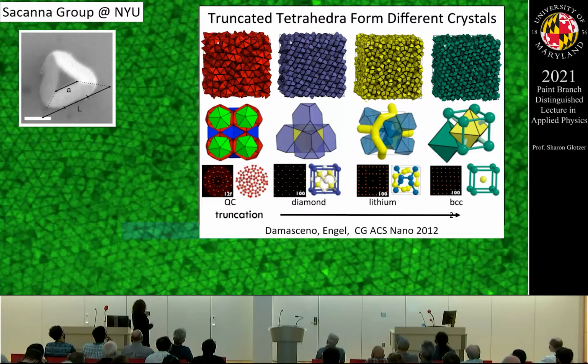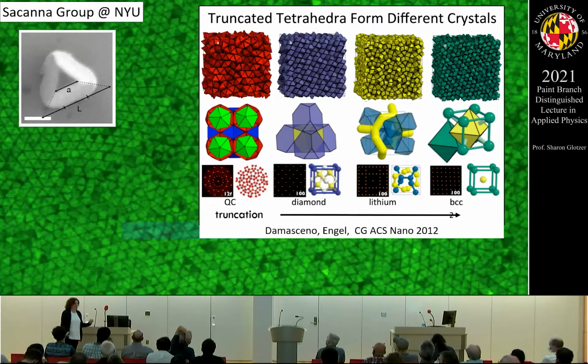This picture that I show behind me is from Stefano Sacanna's group at NYU Chemistry, where he made this truncated tetrahedron, I think again out of polymethyl methacrylate, PMMA, which is really hard to do on a micron scale. It turns out that all of these beautiful nanoparticles that grow as polyhedra are growing as little crystals in solution, and that's why you get these beautiful faceted particles. But on this small scale of a couple hundred nanometers or below, it's really hard to screen out all of the interactions between the particles to really get a hard particle system.